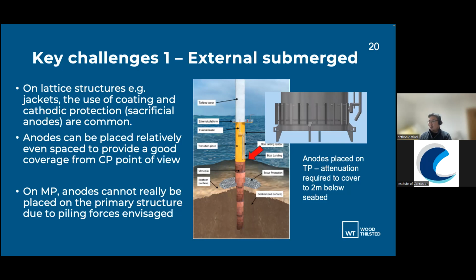Now the problem with a monopile, because of the piling forces that we have when we put the monopile into the ground, the anodes do not really survive those piling forces, and therefore we need to put the anode somewhere else which will not see the piling force, and that can only happen in the transition piece. So the installation sequence, typically the monopile is driven through, and then we will put the transition piece on top, and then the turbine will go above that.